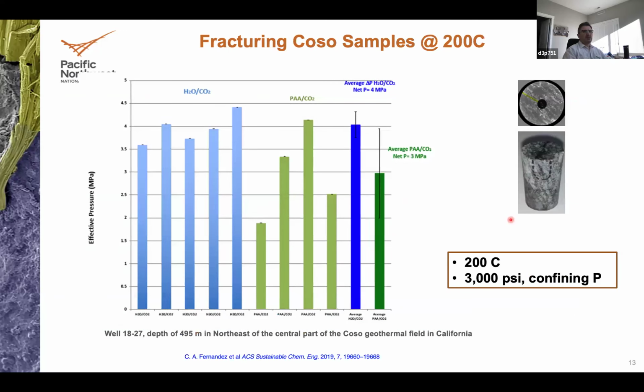And then what we did is basically ran a single core. We got multiple samples, about 9 samples out of this single core of Coso at 200 Celsius. And we repeated experiments, 5 experiments with water CO2, so basically the same experiment in the absence of the polymer, and then with polymer solution CO2. And what we observed was 2 things. One, the variability of the effective pressure, or the breakdown pressure, was very high for PAA CO2, while for water CO2 it was fairly constant. And also that the average effective pressure to fracture this rock was lower, even though the variability was high, compared to the water CO2.